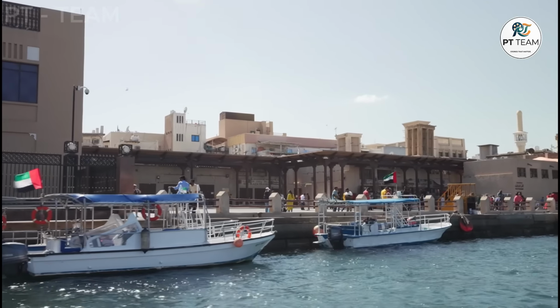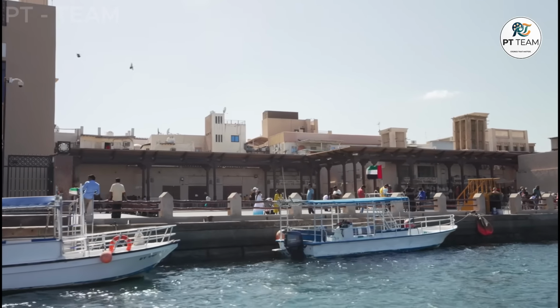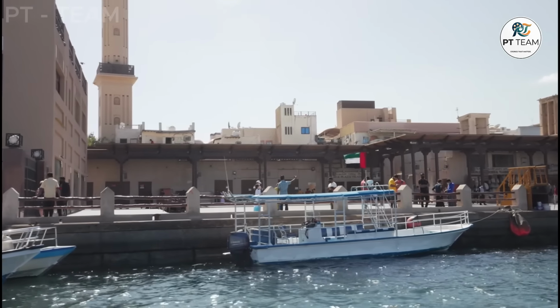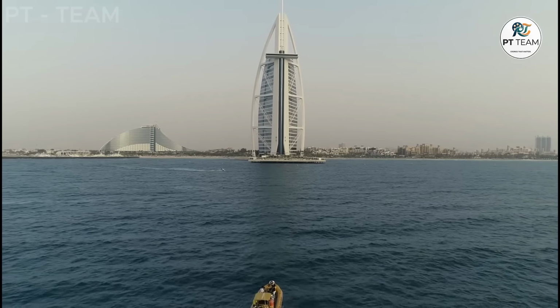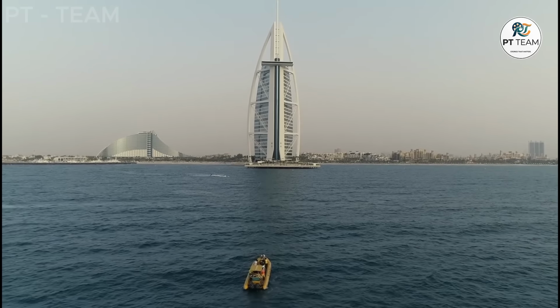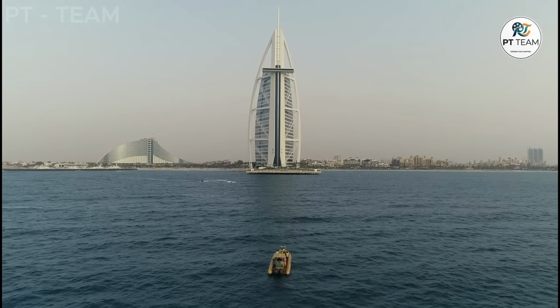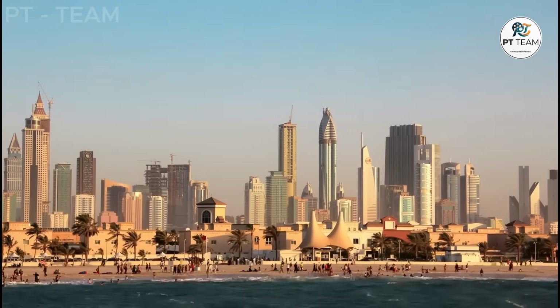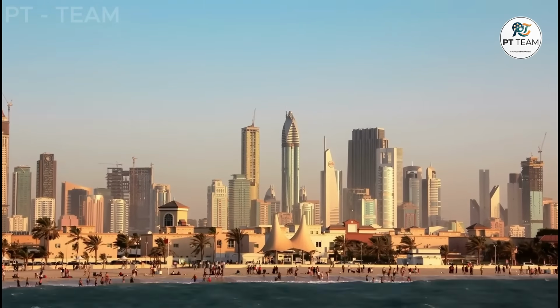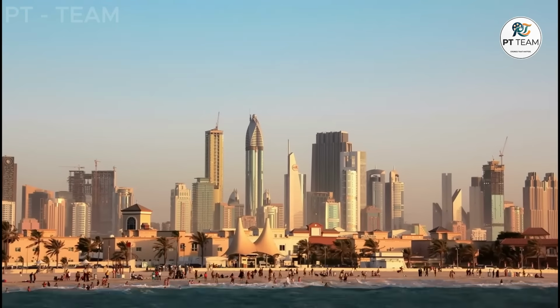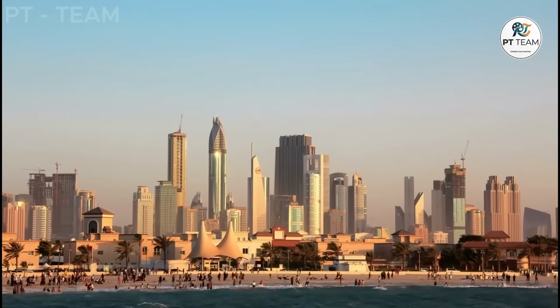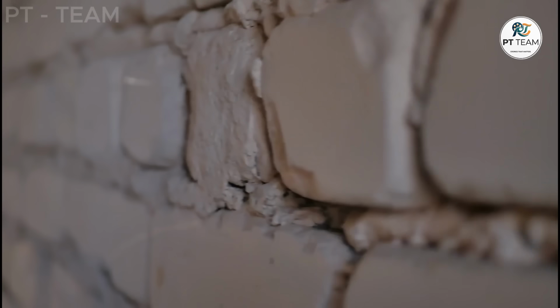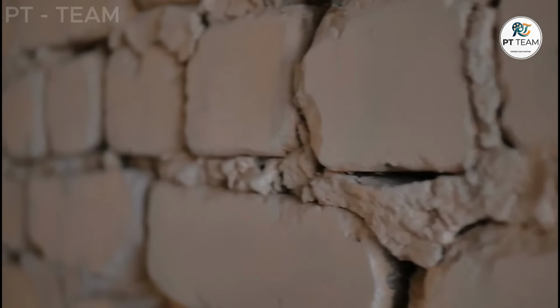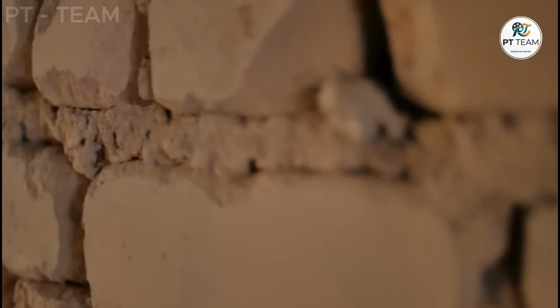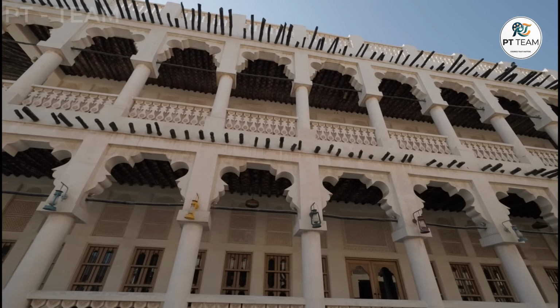Let us look at a typical luxury balcony facing the sea. When it is newly built, it represents the ultimate premium real estate feature. But it is also fully exposed to marine aerosols every single day. The morning condensation wets the surface. The intense afternoon sun dries it out, leaving the salt trapped in the pores. Over a decade, the chloride slowly crosses the threshold. The steel begins to rust. The underside of the balcony develops a hairline fracture. Water from sudden rainstorms seeps into the fracture. Eventually, a heavy piece of the balcony ceiling detaches and falls. This exact cycle does not only happen on balconies.